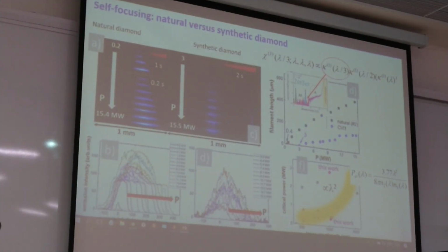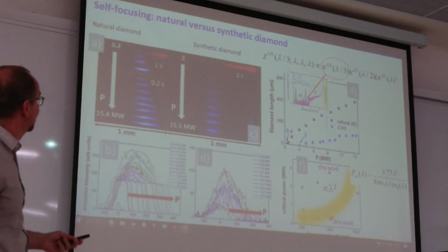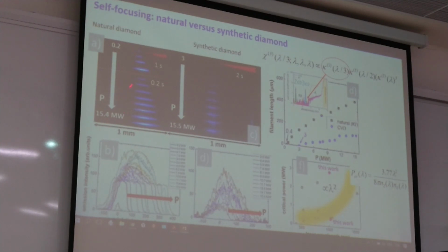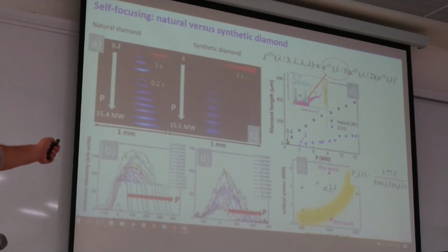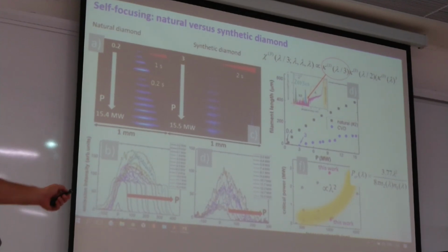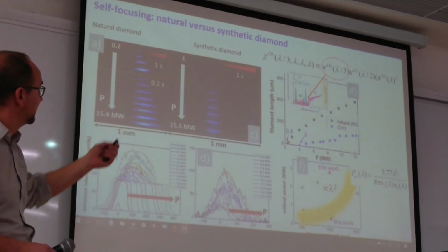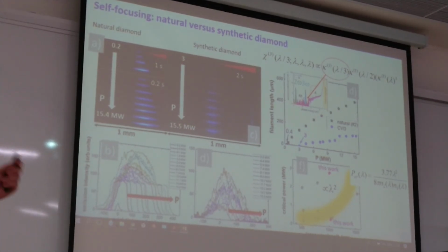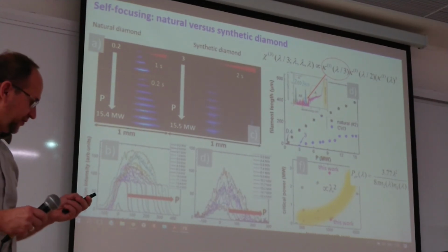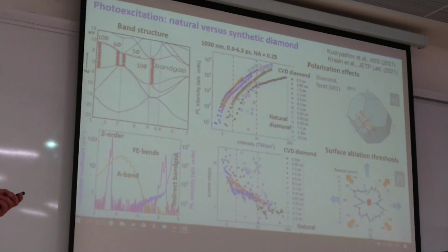For example, if we are focusing laser inside diamond, laser focusing is shown here. The focus depends on the laser parameters, so the peak power of the laser pulse. It goes from linear focusing, so this is the focal position, and it can be extended this way toward the laser because of nonlinear processes like self-focusing. Probably this happens both for natural and synthetic diamonds. So nonlinear interactions related to nonlinear susceptibility are very favored by color centers inside diamonds, but we'll skip this point.